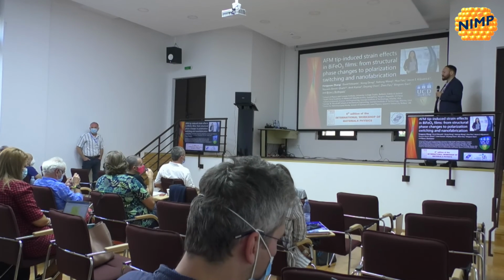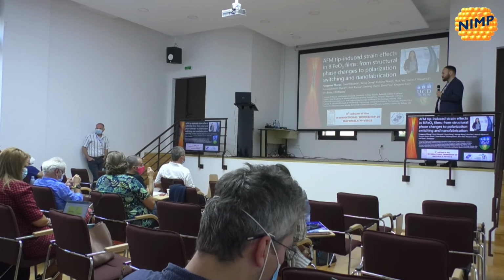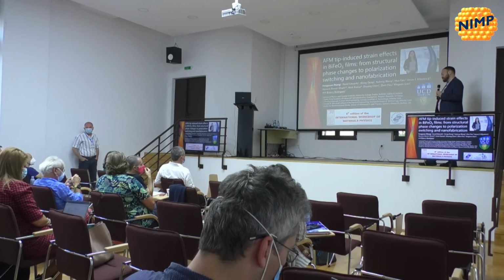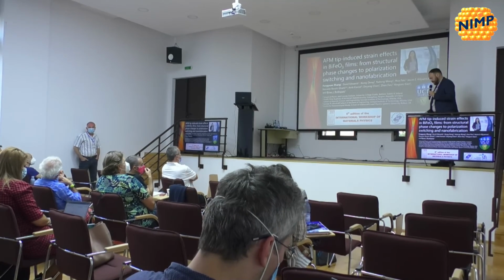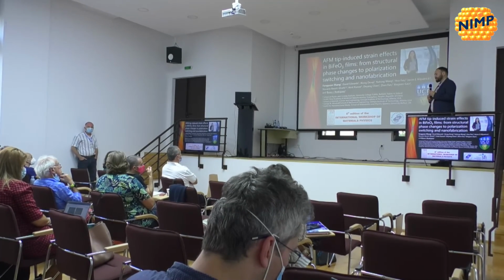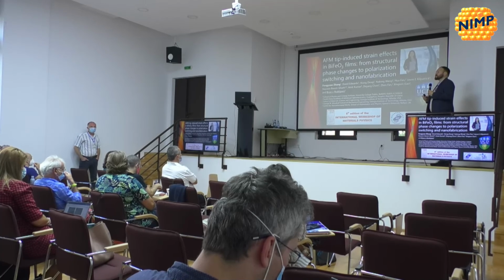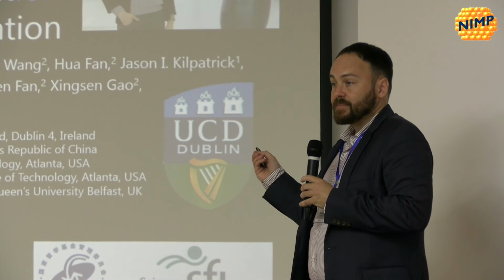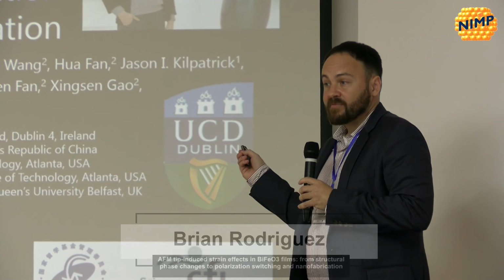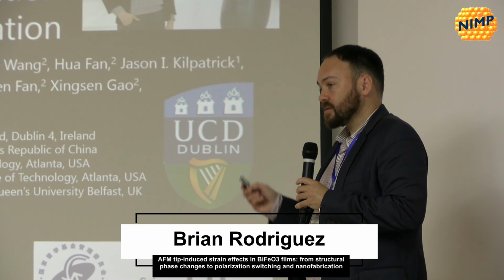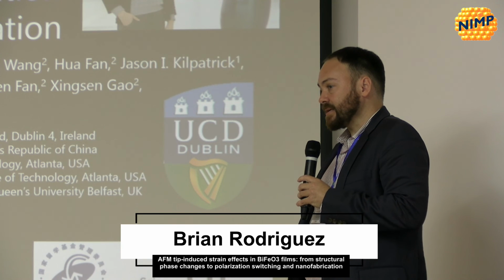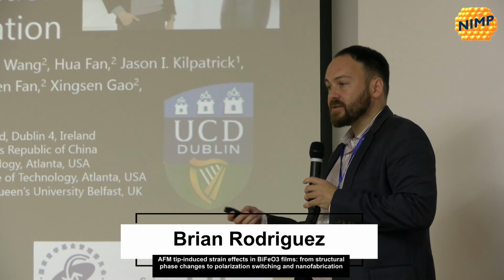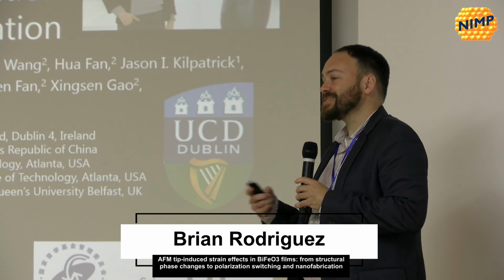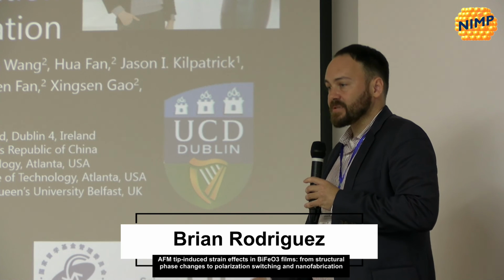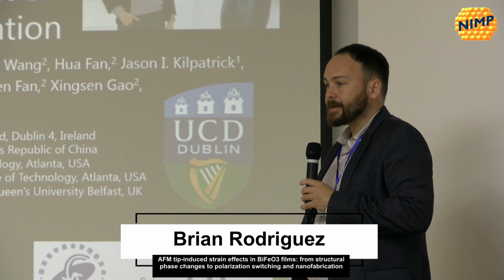But that would be. And for the dead layer itself, how did you identify this dead layer? Because with TEM or with? So yeah, I showed a TEM image, but I wouldn't have been the one that identified it. So our co-authors would have identified it from TEM. But the dead layer has been reported to exist in similar thin films, BFO films of this thickness. Okay.